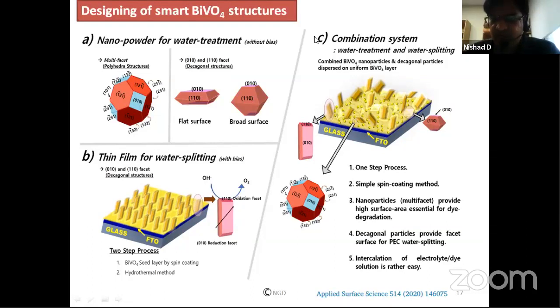So what we did is we combined this structure, and we tried to see what will happen if we have two different kinds of facets in one structure. We used a simple process in which we use simple spin coating methods, and we achieved the nanoparticles, and then we controlled the facets in such a way that we can have two different facets, and we studied the PEC water splitting mechanism of this.